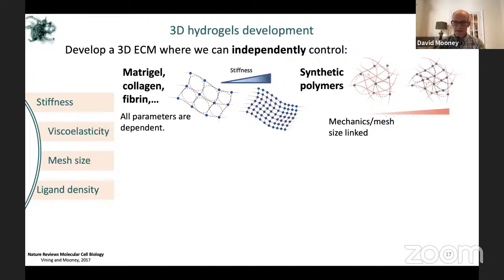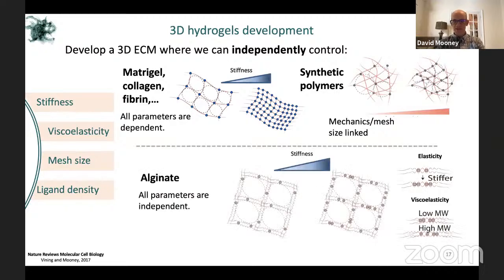Now we can take a classic synthetic polymer approach to make hydrogels instead. Like the alginate system, if the cells don't mediate adhesion themselves, we can decouple the ligand density and type by covalently conjugating it to the polymer chains after we form them into gels that are either more or less stiff. But again, as one varies the cross-link density in a traditional polymer system, one varies the mesh size or diffusional transport. Now, the reason we use these alginate gels is because of this cross-linking structure, or this cross-linking between blocks of these sugars that I previously described.